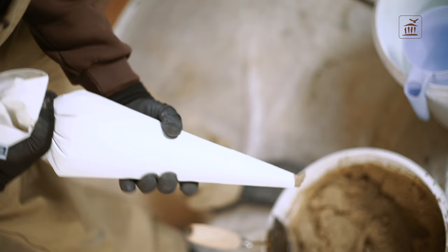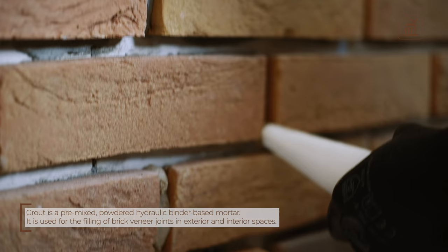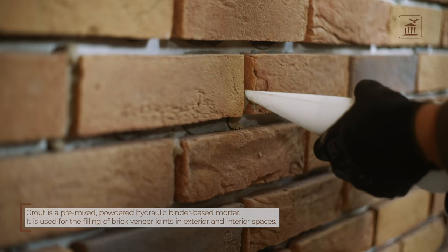If prepared in the right consistency, it does not flow easily and does not stain the surface of brick easily. Depending on surface conditions and temperature, for more absorbent surfaces or in hot weather, keep the mixture a little more liquid and keep it denser in wet or winter conditions.